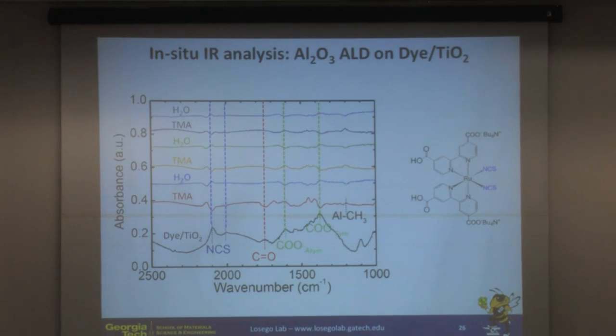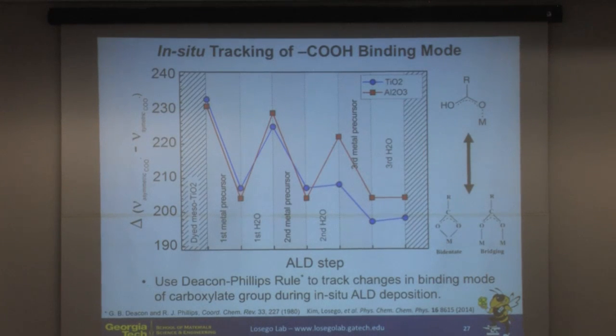And if you look very closely, it's actually a shift that we're seeing. So we're seeing these asymmetric and symmetric stretches sort of getting closer and farther away from each other. So we plotted that difference in the symmetric and asymmetric stretching modes of these COO groups. And we see with each half cycle, we're sort of oscillating back and forth with both precursor chemistries that we're using. And what that sort of indicates, and this is somewhat interpretive of what we're observing, is a change in the binding state of this COO group from a monodentate to a bidentate. So the water is probably releasing this from a monodentate to a bidentate sort of binding group.